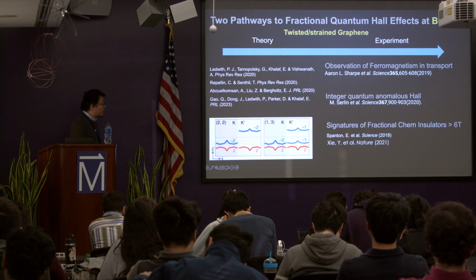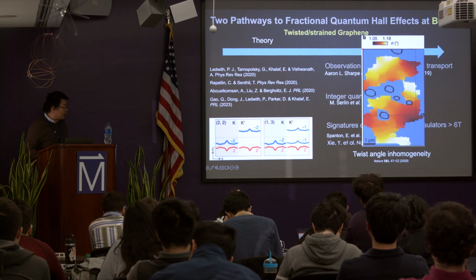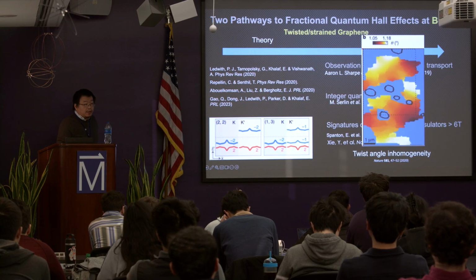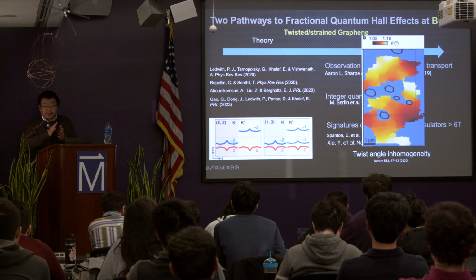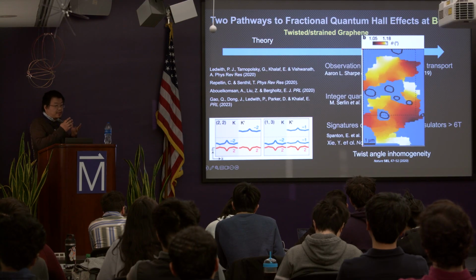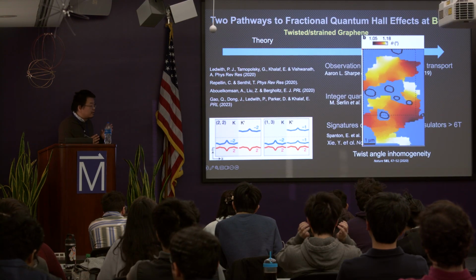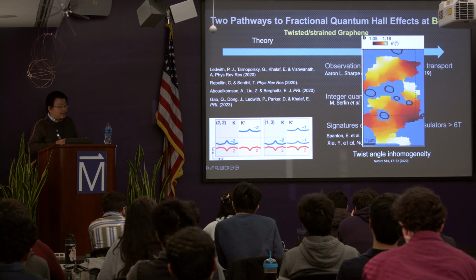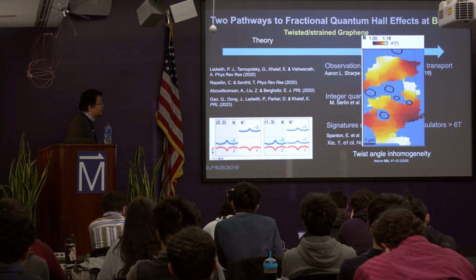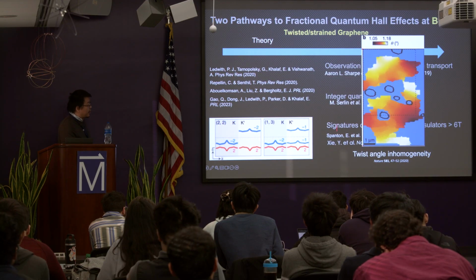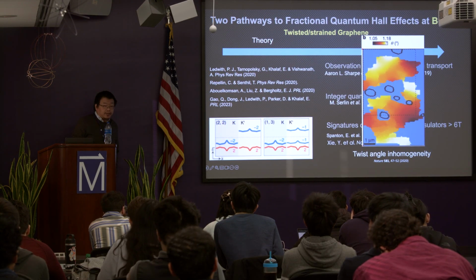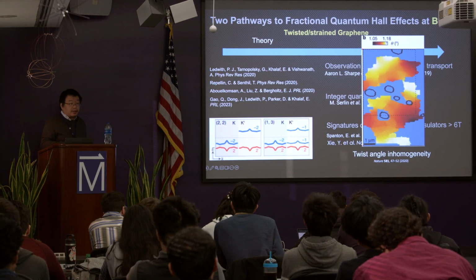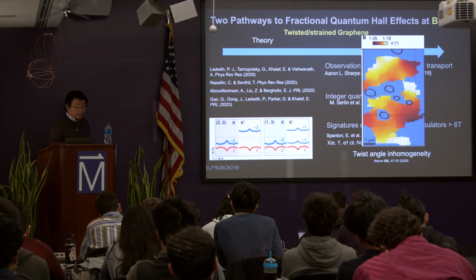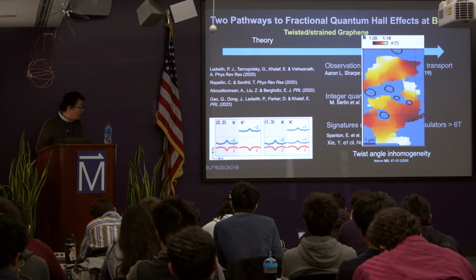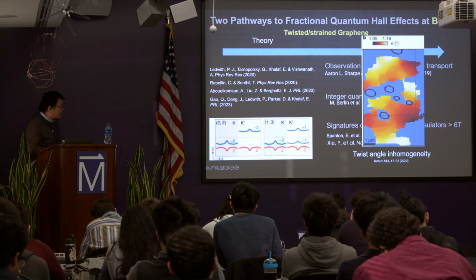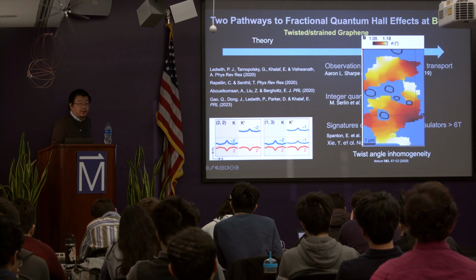So you're not really nailing down such a state at zero magnetic field, and it's not really a transport measurement. The issue here is actually coming from the so-called twist angle inhomogeneity. You have two layers of single-layer 2D material. When you twist them, they will naturally relax to a certain angle, right? So not necessarily will the whole device give you a single, uniform angle. As you can see here, if you map out the angle, there's a pretty large variation, and this will kill whatever property you want to measure globally, for example, like transport. So far this is the best effort along twisted bilayer graphene.